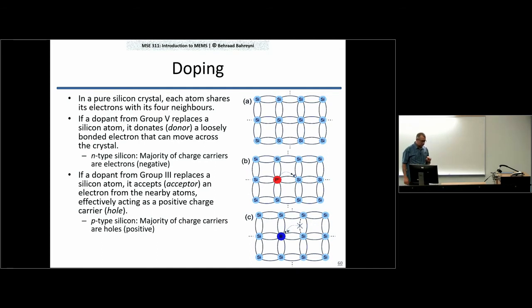Now, same thing as what we had for the donors. We call it an acceptor here. The boron, we call it an acceptor dopant here because it is accepting one electron from the lattice. It is a positive charge carrier that it donates, so it is a p-type. But again, you can see that for every boron atom that is ionized, you get one charge carrier in the network. So for every boron atom, you get more charge carriers. If you increase the number of boron atoms, you will have more holes. So therefore, better conductivity, electrical conductivity.